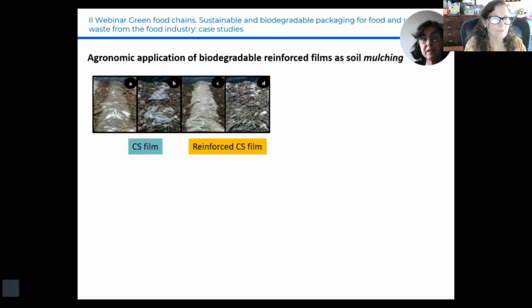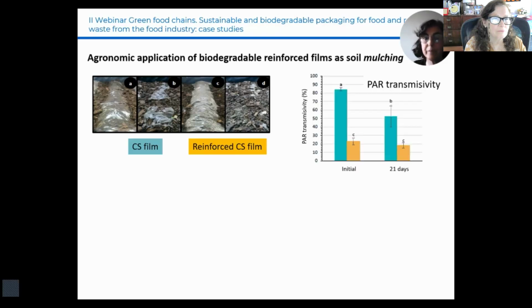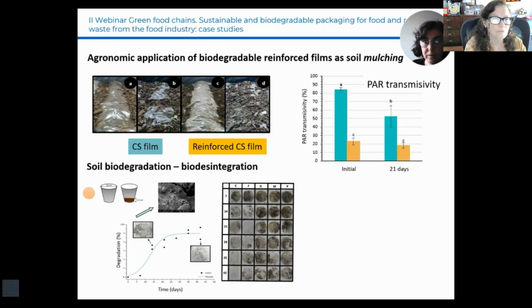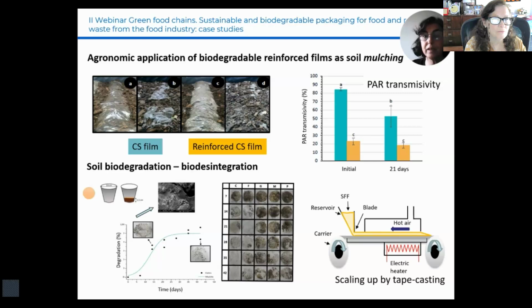In this case, cassava starch-based films reinforced with bagasse were used as soil mulch under real field conditions. As you can see in the photographs, these materials began to degrade after 21 days of exposure to air. During this time, a decrease in PAR transmissivity was also observed. When their biodegradation in soil was evaluated, 42 days were required for complete disintegration. These materials could be easily obtained using the tape casting technique and would be suitable for short-cycle crops.